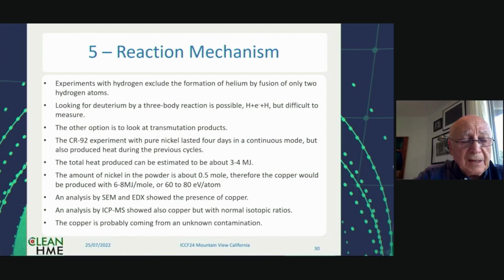Okay, now we have shown that we have excess heat. Now, what's the reaction mechanism there? Experiments with hydrogen exclude the formation of helium because it's difficult to do that with 2 hydrogen atoms. Looking for deuterium by a 3-body reaction is possible, like H plus e plus H, but difficult to measure in a hydrogen environment with a low resolution mass spectrometer. The other option is to look for transmutation products.